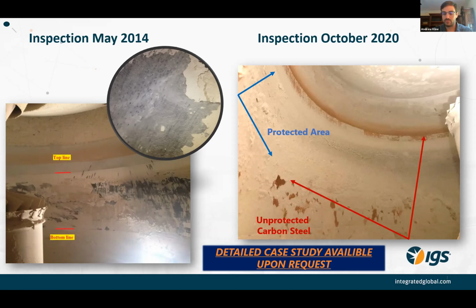Now we talked to the plant and said, hey, make sure to pay attention to those areas because, and this is what we've told everybody now, once you've coated the 90% of your problem, which is typically your spray affected zone or the crease in the cone, well, then people often just fix the problem and move on to the next thing. But 10 years later, you can come back and you've fixed your bulk of the area, but that area above and below still needs attention, because if you neglect that, over time you can have a failure in that region. But a detailed case study with some more photos and more detailed information of this is available.